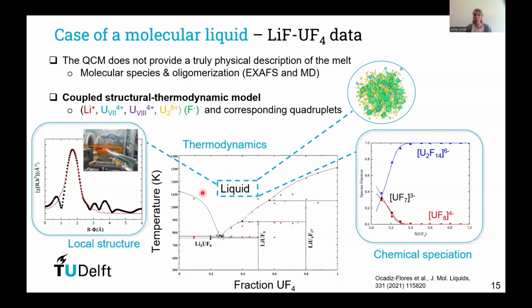some insight on the structure of a liquid as we know it from the experiments and from the molecular dynamic simulations. So with this kind of description, we can also reproduce the chemical speciation from the molecular dynamic simulation. And this is what you see here, where the line, which is the Karlsruhe model, also reproduces the speciation of the monomeric species, the 7-fold and 8-fold coordinated uranium, as well as the progressive formation of polymers in this melt when the uranium content increases. So this is the first type of model I wanted to show today.